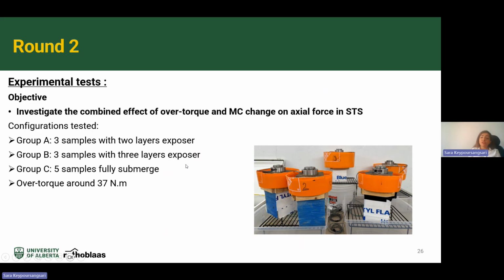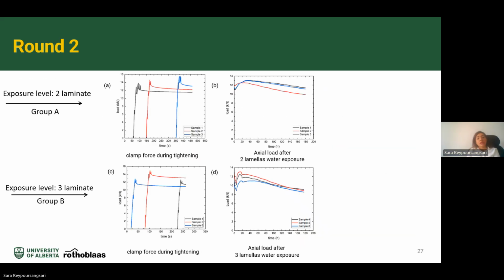In group A, only 2 layers of glulam were exposed to water. In group B, 3 layers were exposed to water. And in group C, we wholly submerged our glulam into the water. In this round, as you can see here, same as the previous round, we applied the torque, and we over torque the screws until 37 Newton meter. In this stage, we didn't stay for the relaxation phase, and we poured the water only a few minutes after the installation, and you can see the results.